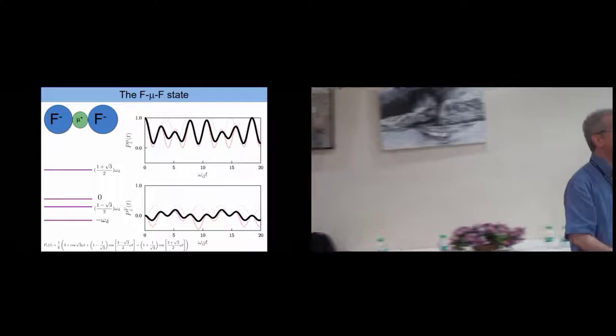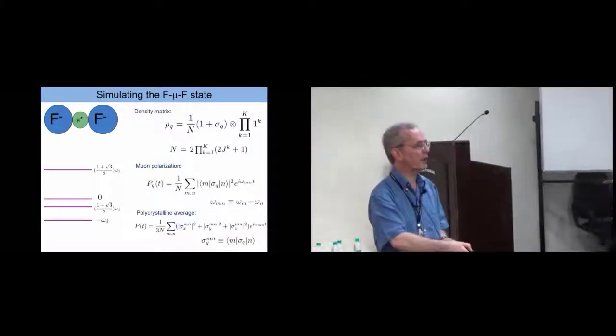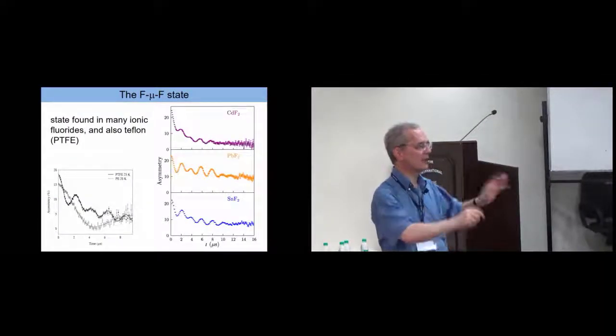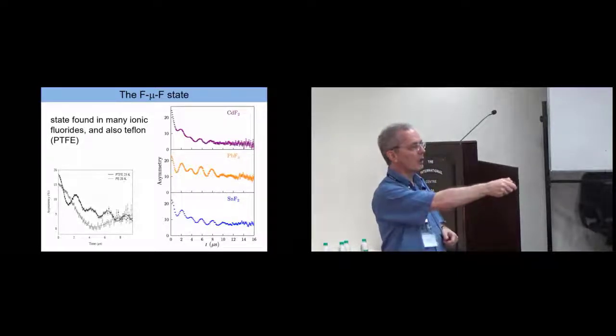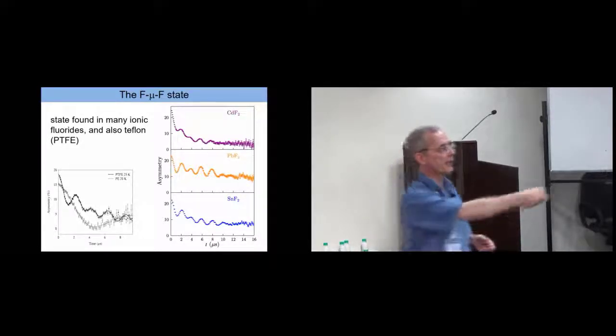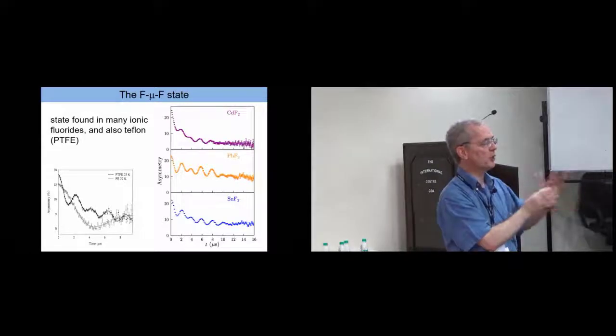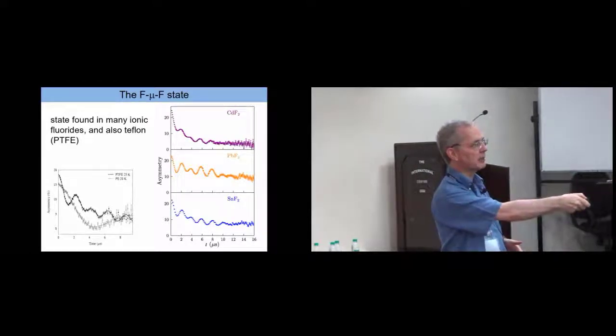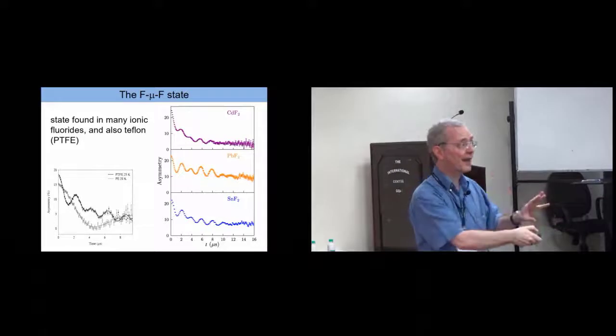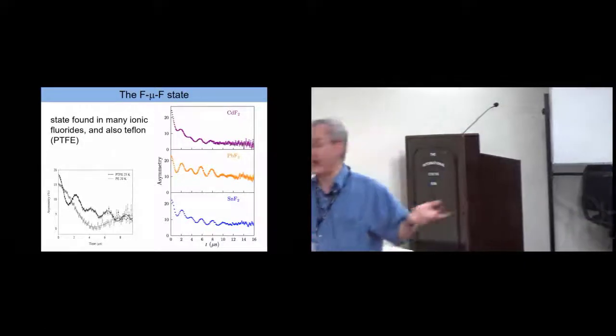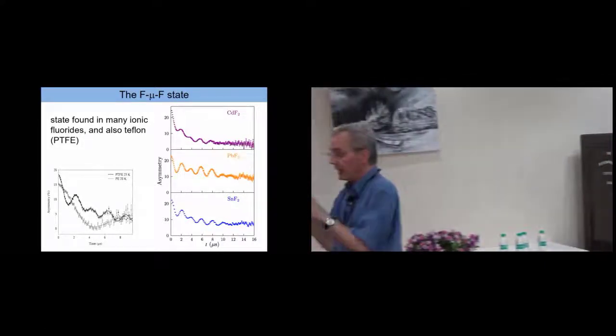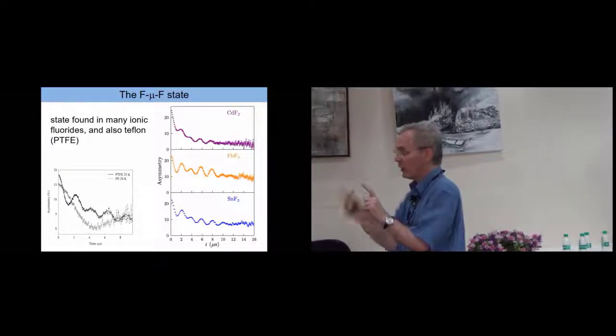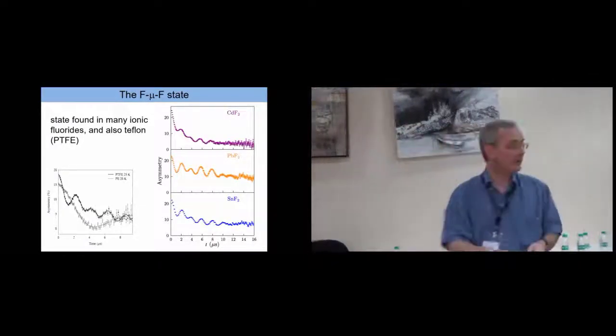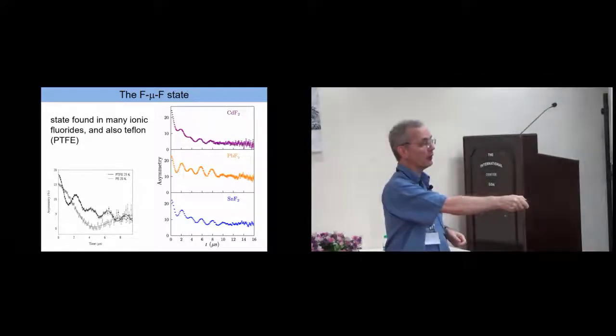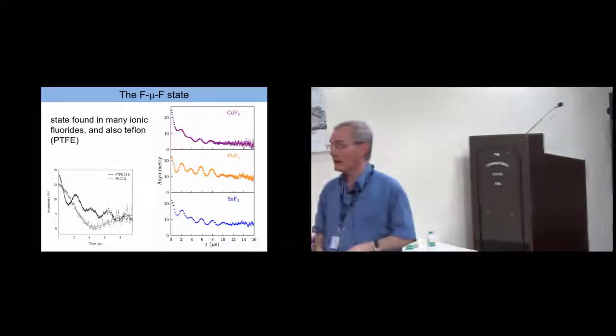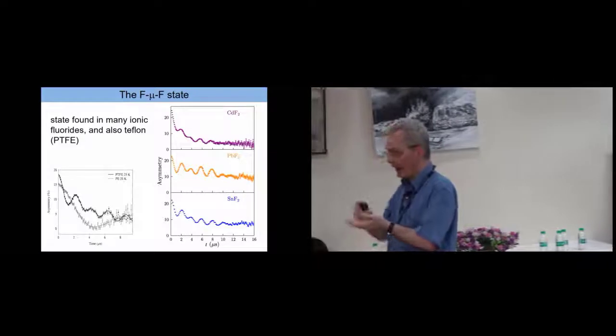And interestingly, this is actually seen in experiments, so I won't go through the mathematics of how you work this out. It's a simple quantum problem. But this is actually seen in many materials. So this transfer of polarization between the muon and the fluorines giving this beating pattern is seen in these materials. These are non-magnetic: lead fluoride, tin fluoride, cadmium fluoride. So what you're seeing here is a resonant transfer of polarization between the muon and the fluorine ion. And you even see it in Teflon, PTFE. So this is a very common thing.